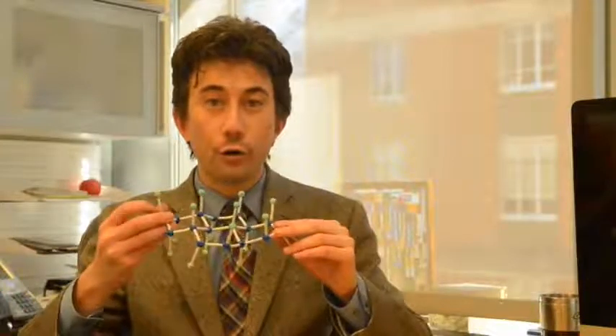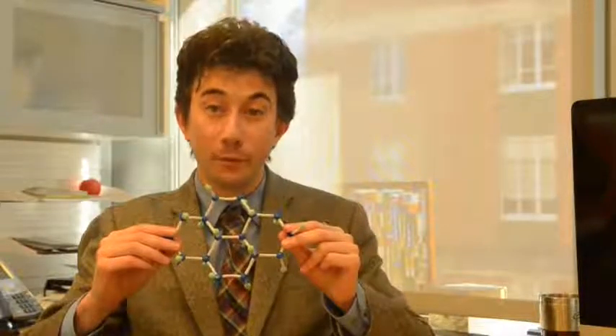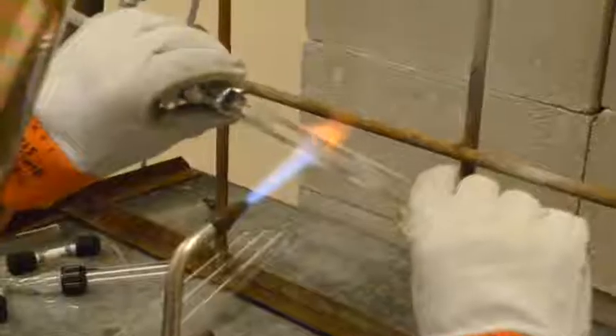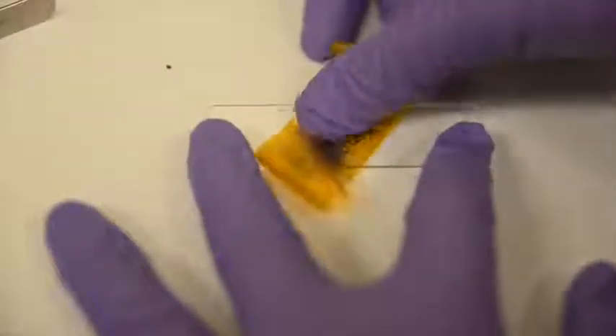However, in order for this single layer of germanium atoms to be stable, every atom needs to have the same number of bonds as in the original germanium crystal, meaning that we need to terminate the top and the bottom of the layers with a chemical group. We call this material germanane. We have learned how to grow crystals consisting of sheets of germanane that are stacked together. These crystals can be exfoliated down to single layers by fitting them between pieces of tape and stamping them onto substrates where we can then study their electronic properties.